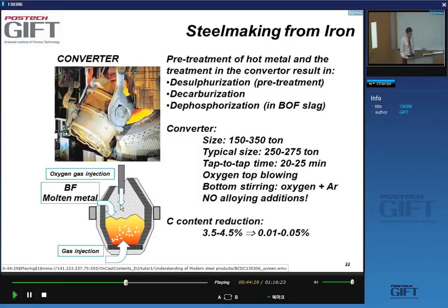First of all, basic is because we have the lining, which is basic, alkaline material, alkaline stones, no silicates. The oxygen refers to the fact that we are getting rid of the carbon and producing heat by basically blowing oxygen, injecting oxygen on top of the molten metal. And we also bubble argon through little openings in the bottom of this converter.